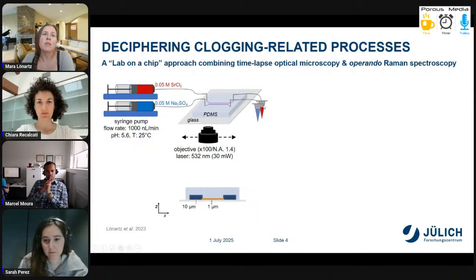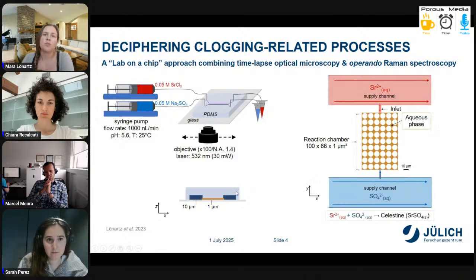You have a PDMS glass chip, and on the left side, two reactants were injected at the same concentrations, going through the supply channels, and on the right side there's the outflow. Those channels had a height of 10 micrometers and were connected via a porous reaction chamber just 1 micrometer in height. The idea was to generate a constant high flow rate so that we have a constant concentration, triggering the precipitation by counter diffusion of celestine.